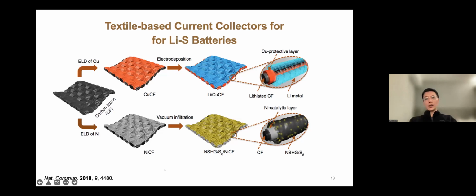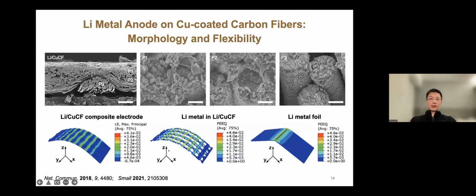All right. So this is how the lithium metal composite anode looks like. Nowadays there are many similar publications showing similar images. Basically, in the cross section, you'll see hundreds of thousands of fibers, and each of the fibers is conductive. It was coated with lithium metal, either thick or thin. And what we found through the experiment, and also the result here of our simulation, is that when you bend this composite, which is on the left-hand side, you don't really see a high level of stress localization, right? You do see something, but it's not high.